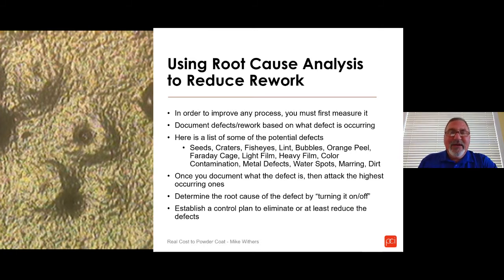Many companies, in my experience, do a really good job of measuring the reworks they had, but what we don't measure oftentimes is the cost of the rework. If you are having to go back in and scuff parts, burn off parts, or send them out for chemical strip, and you start to document all those costs and look at what is causing the defect, if you attack the ones that are occurring the most by figuring out the root cause and turning off the defect, then you're able to significantly impact the cost to coat.